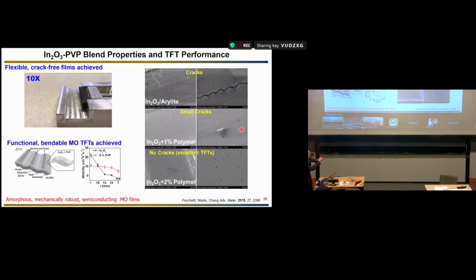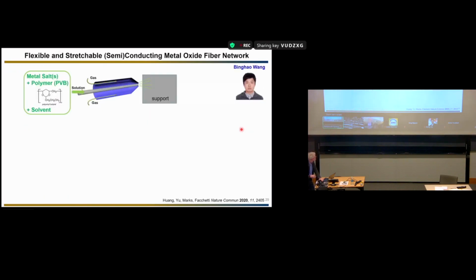For example, this is the performance of indium oxide. These are the initial performance if you don't use any polymer. If you use a little bit of polymer, you sacrifice the initial performance, but then the performance remains much more stable when you start bending the substrate. So that was one way to enhance ductility.